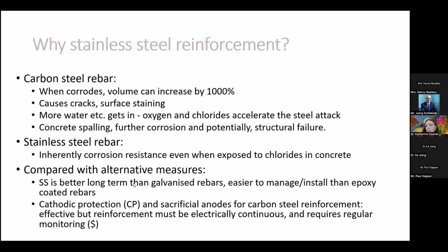So why would you use stainless steel reinforcement? So again, the obvious one is the corrosion resistance, but drilling into that a little bit further, carbon steel reinforcement obviously corrodes when exposed, but when it does corrode, the volume of it can increase by up to 10 times the original cross-sectional volume, which can cause cracking and surface staining in the surrounding concrete. This, of course, means that more water gets in, the oxygen and the chlorides can accelerate the attack on the steel, which further propagates the problem. This can lead to concrete spalling, further corrosion, and ultimately and potentially structural failure.